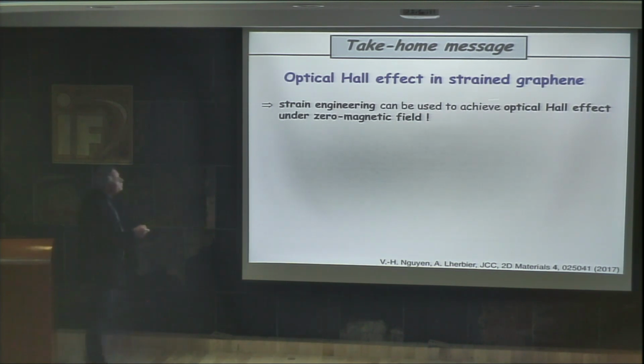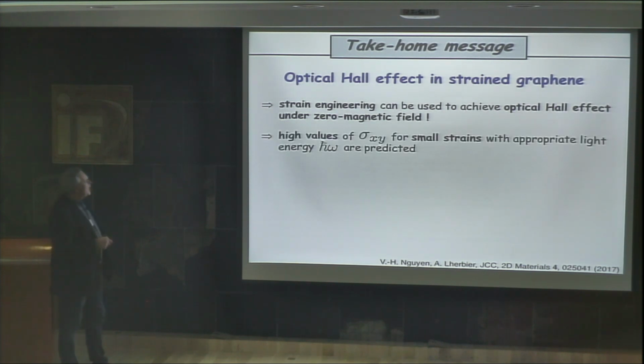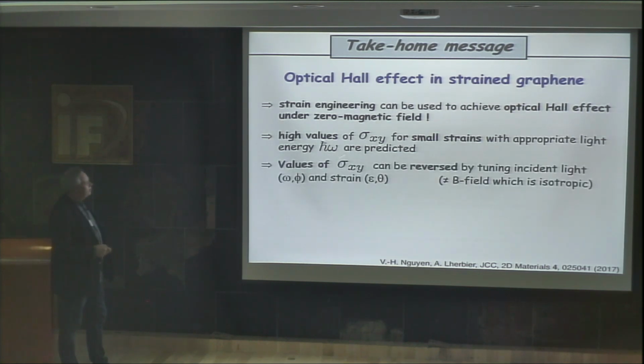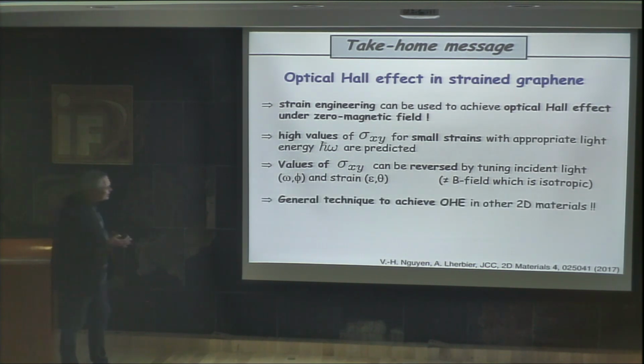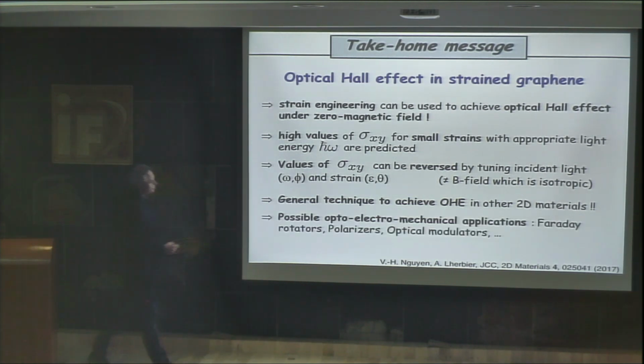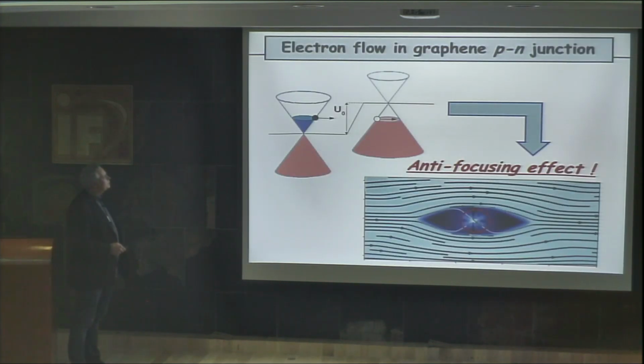Strain engineering can be used to achieve optical Hall effect under zero magnetic field. High values of sigma xy for small strain with appropriate energy are predicted. The value of sigma xy can be reversed by tuning incident light and also strain. It's a general technique to achieve optical Hall effect in other 2D materials. And there are possible electromechanical applications using this specific effect.